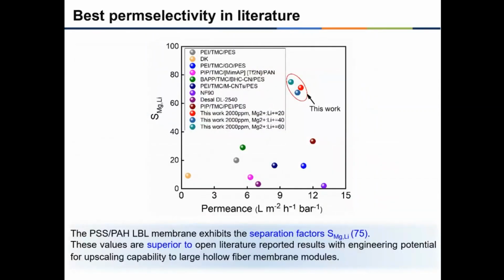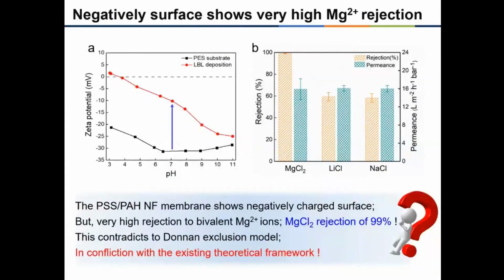We further compared the performance of our LBL nanofiltration membrane with results reported in the literature. The PSS/PAH bilayer LBL membrane shows the highest separation factors. The membrane surface was negatively charged at pH 7 according to the zeta potential measurement. Based on Donnan effects, magnesium rejection should not be very high. However, the nanofiltration membrane rejection of magnesium is about 99%, which is extremely high. This contradicts the Donnan exclusion model.